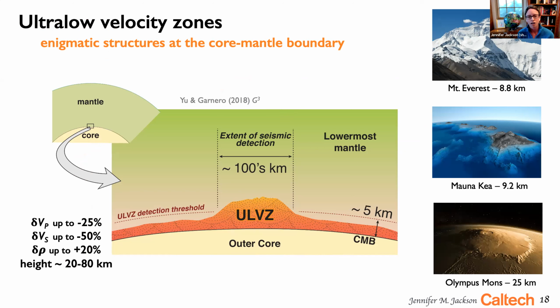several decades-long research in identifying these structures using seismic waveforms. From many of these studies, we can briefly summarize what they are. The seismic waveform studies have constrained extreme velocity reductions. Shear waves have been shown to be depressed by up to 50% relative to the surrounding mantle, with thickness estimates ranging from a few kilometers to about 80 kilometers or so. Just a few references here: Mount Everest is 8.8 kilometers, Mauna Kea rises 9.2 kilometers, Olympus Mons is 25 kilometers. So these are the scales of these features. They're actually not that small.